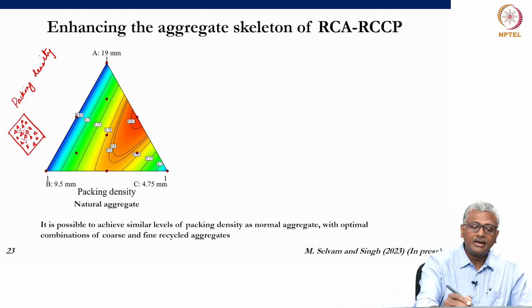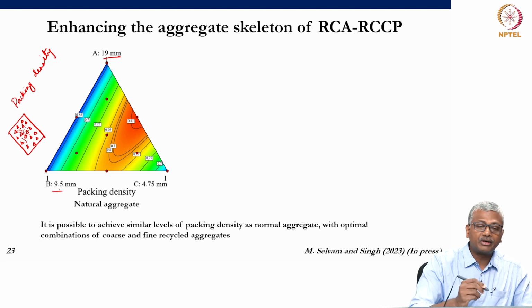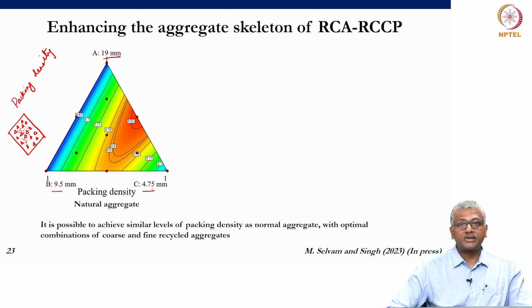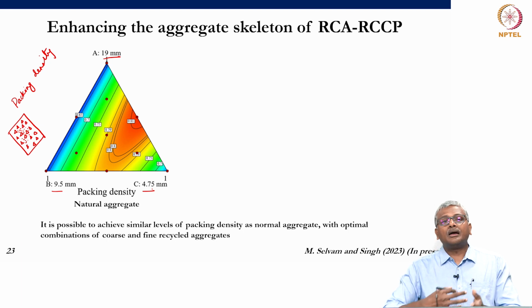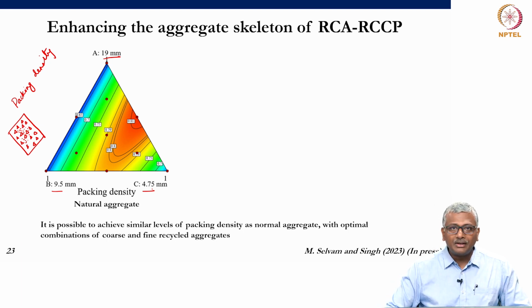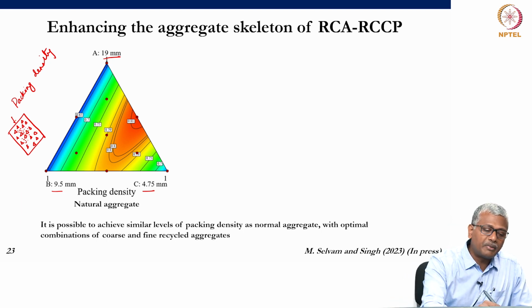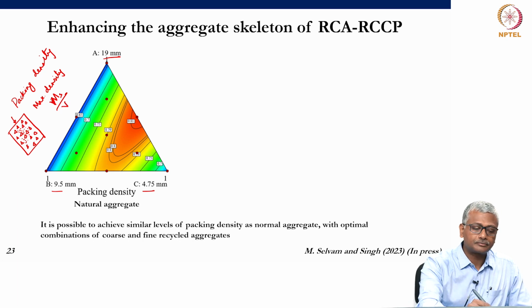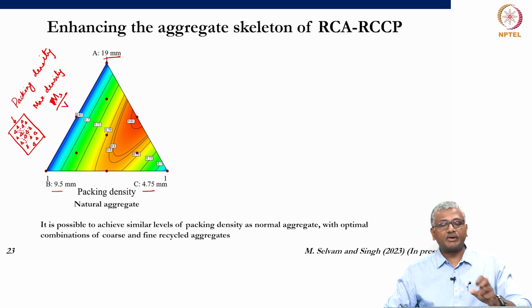For instance, when you have a 19 millimeter aggregate, a 9.5 or 10 millimeter aggregate and a 4.75 millimeter fine aggregate, then in what proportion should you blend it so that you get optimal packing? What is optimal packing? Optimal packing is when you get the maximum density, which is equal to the mass of the solids divided by the volume of the container. The mass of the solids in the system divided by the volume of the container. So, that is the packing density of the system, right.